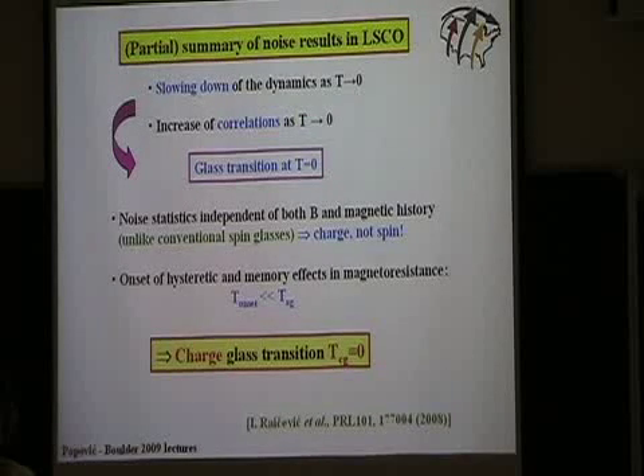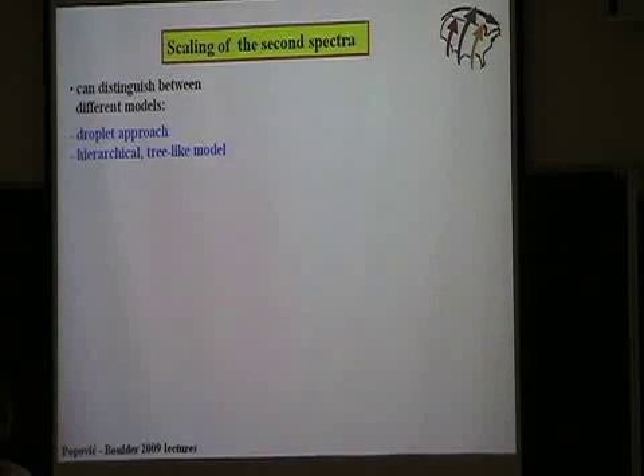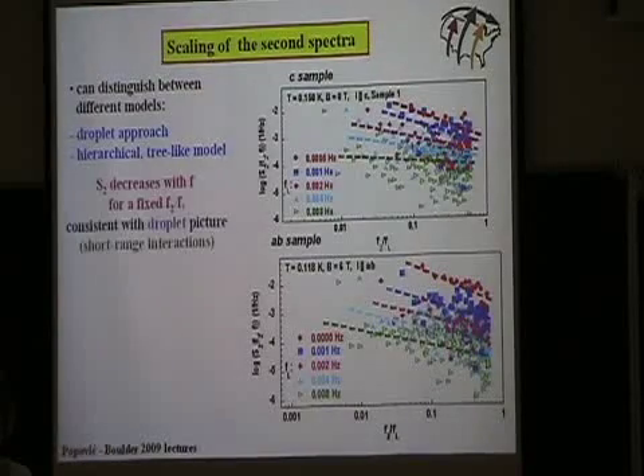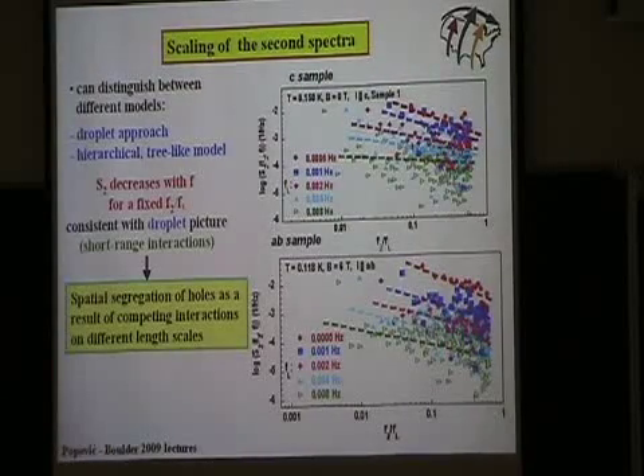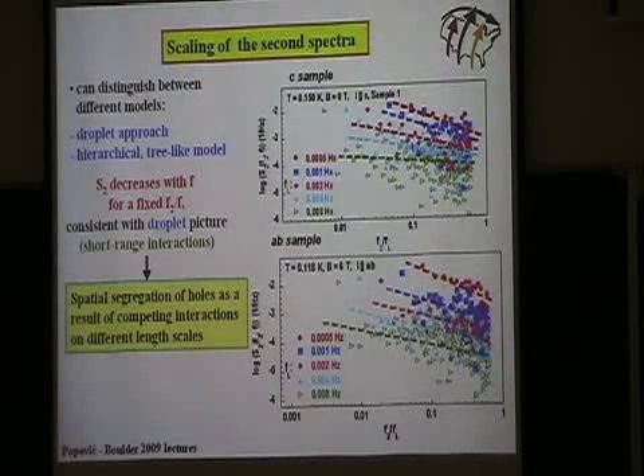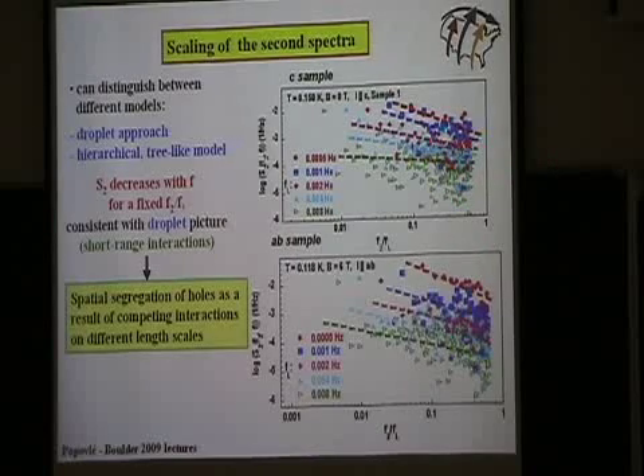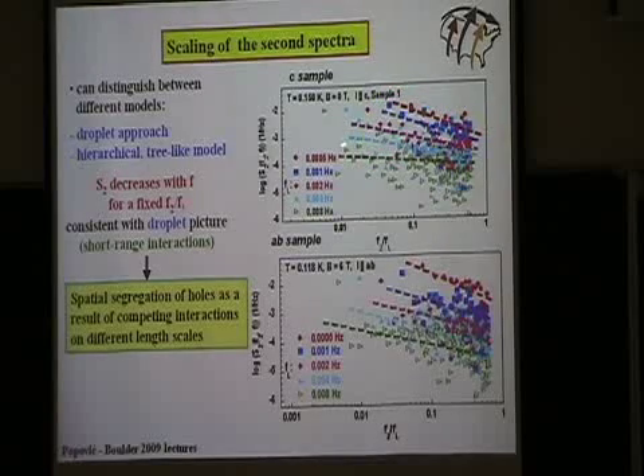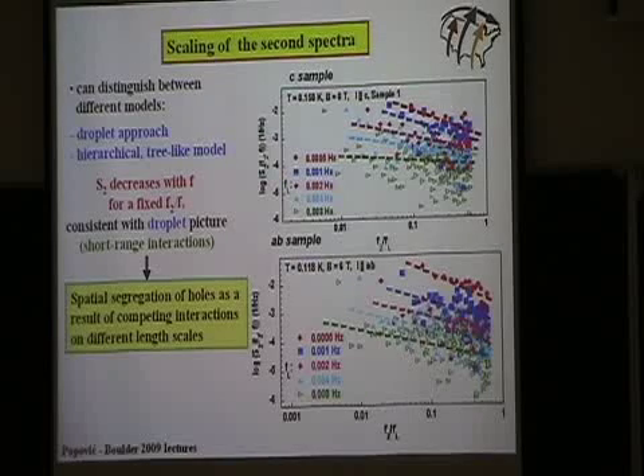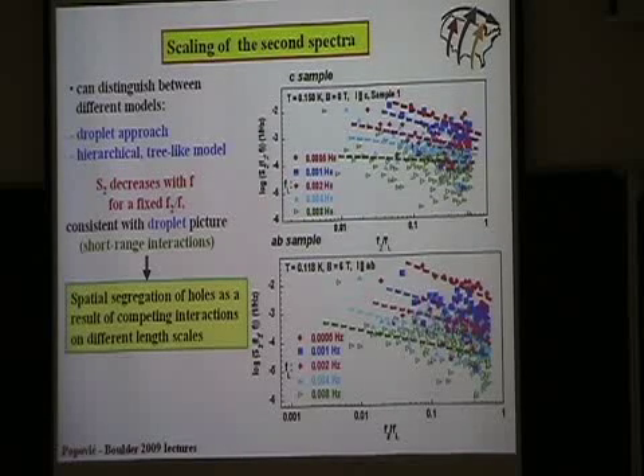So what about scaling? Okay, can we say something about that? So I already mentioned that before. And here are the data, and I hope you can see that even though they're noisy, they're very different from what I showed you for silicon MOSFETs, where even within the noise, there was no systematic dependence on frequency. And here we see a clear dependence for both in-plane and out-of-plane transport. So it seems that in this case,